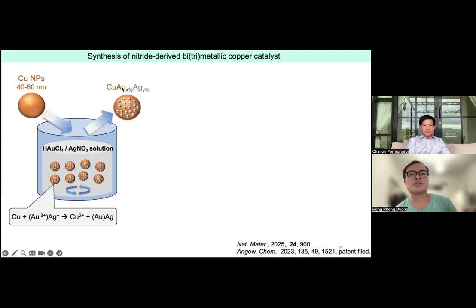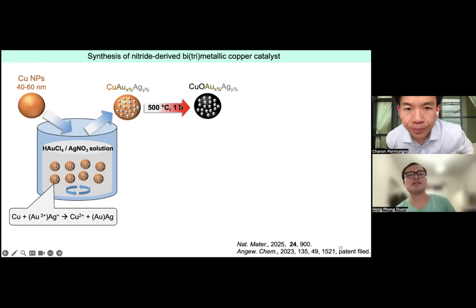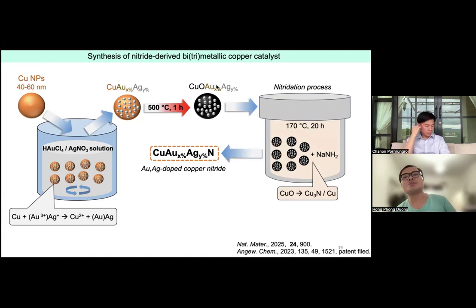The trimetallic, which contains silver and gold doped into copper, and then you perform the oxidation or calcination in order to convert all of this copper into copper oxide. And then you perform the nitridation process, which means you mix with sodium amide inside an autoclave, and you perform the heating process, and over 20 hours you can dope nitrogen into copper. All of this copper oxide would be converted into copper nitride, with the presence of gold and silver doping as well. All these materials start to look very complicated.